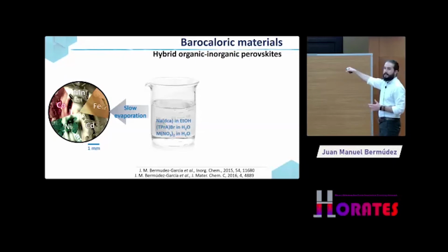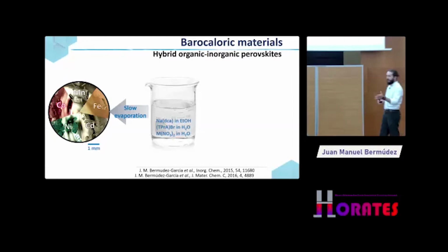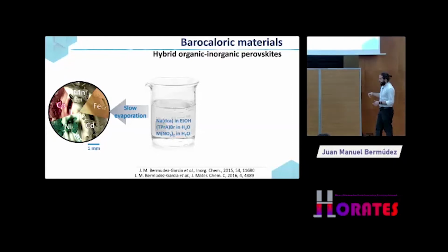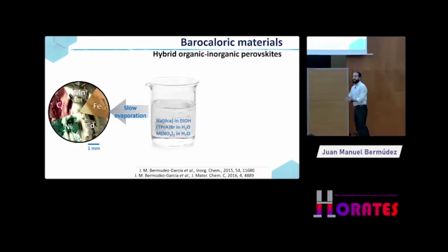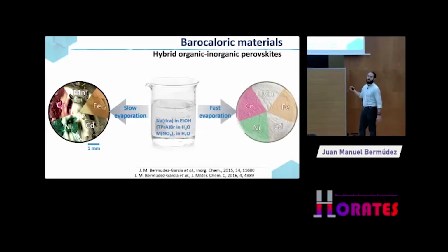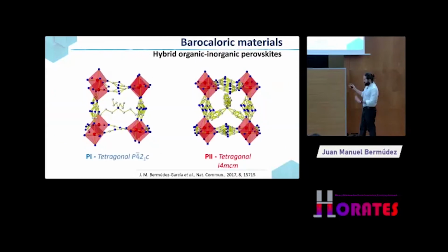So we can do the whole characterization in single crystal, but the size is on the millimeter scale. We were able as well to decrease the evaporation time, which was between a week and a month. But if we increase the speed of the evaporation with a rotary evaporator, in terms of minutes, we were able to obtain the same materials but in the form of fine powders. So that will be very interesting for the industry, right? Well, that was a small clarification.